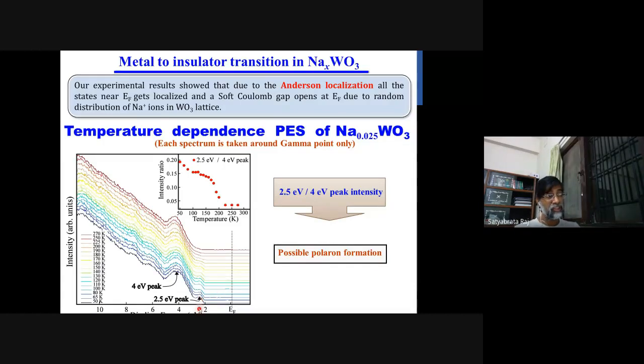Surprisingly, we see that the density of states at 2.5 eV just vanishes at 230 Kelvin. That indicates a possible polaron formation when you increase the temperature beyond 230. The polaron is nothing but the electron given by the sodium, dressed by the phonon and the lattice. And that polaron is no more at the site, so the density of states spreads all over the Brillouin zone, no longer centered at gamma. Most of the density of states arises at gamma below the polaron formation temperature. Above the polaron formation, the density of states should spread over the zone.